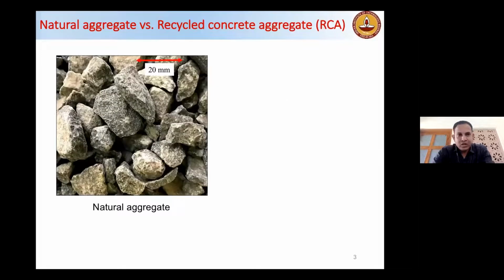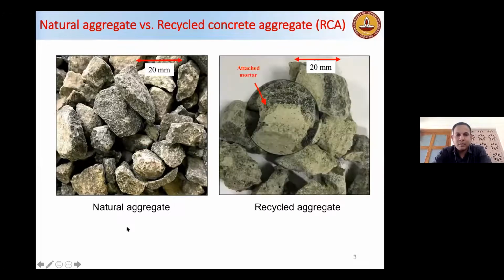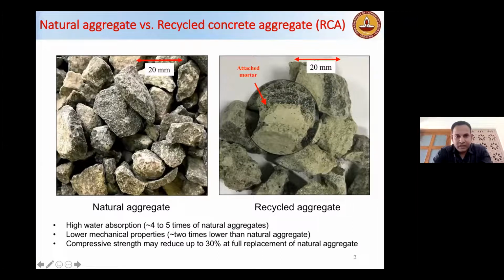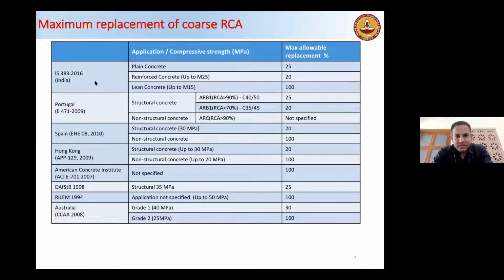So this is the natural aggregate, and this is the recycle aggregate. So as Professor Surender already mentioned, this is the attached mortar here, and it is responsible for the higher water absorption, which is the main problem, and the mechanical properties are lowered. And then if you fully replace, it can reduce the concrete strength up to 30%. And then you have already seen this.